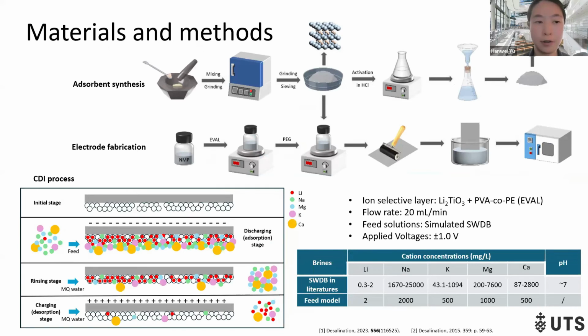And here are the materials and method. The ion selective layer was fabricated using lithium titanate and a polymer called EVAL. The EVAL contains PVA and PE parts, where one side is hydrophilic and one side is hydrophobic. So one side can provide the strong structure, and the other side can provide contact with water, which benefits the ion adsorption. And in this research, for the feed solution, we used simulated seawater desalination brine based on the literature results.